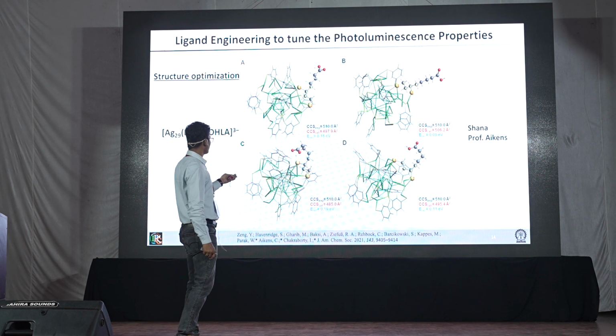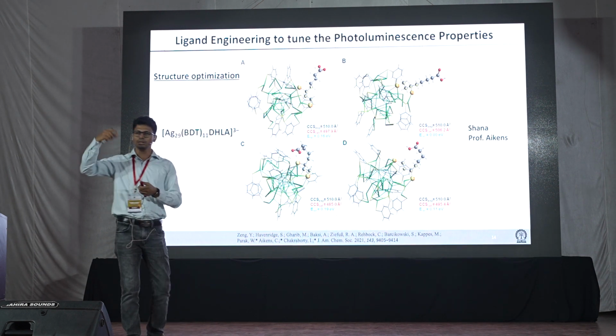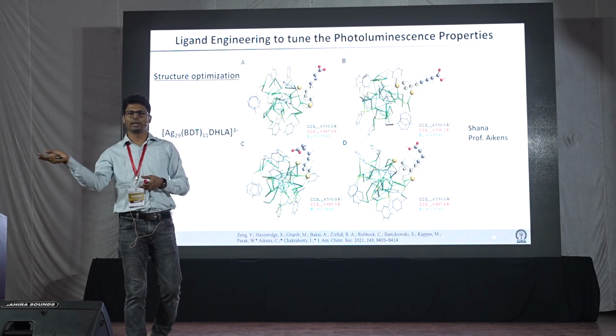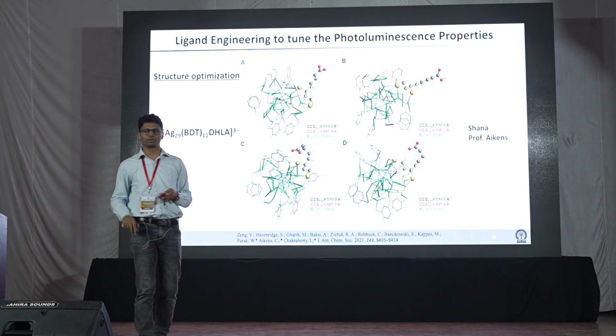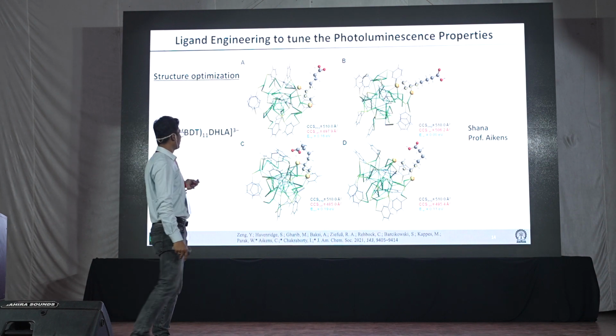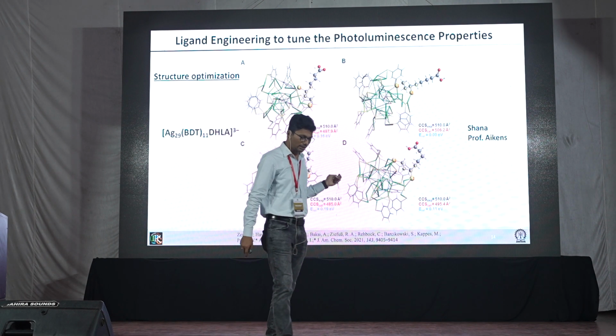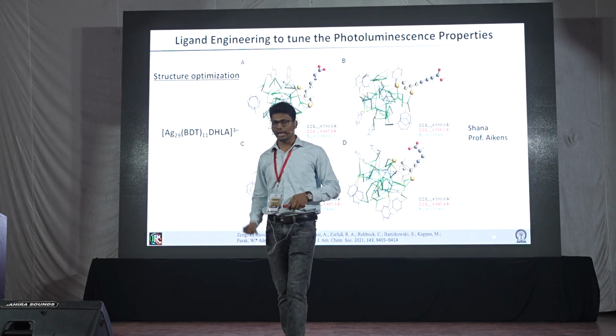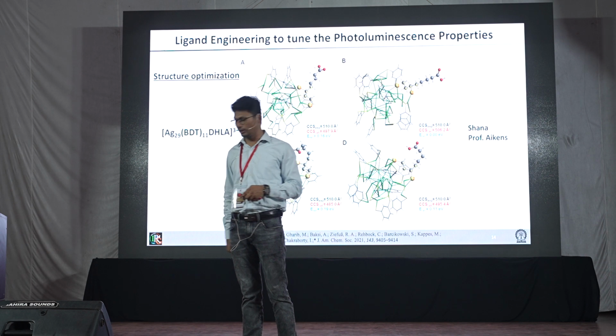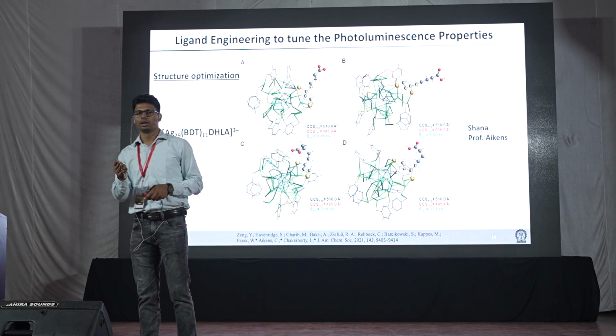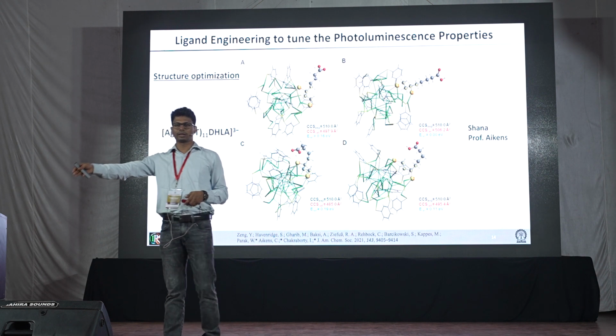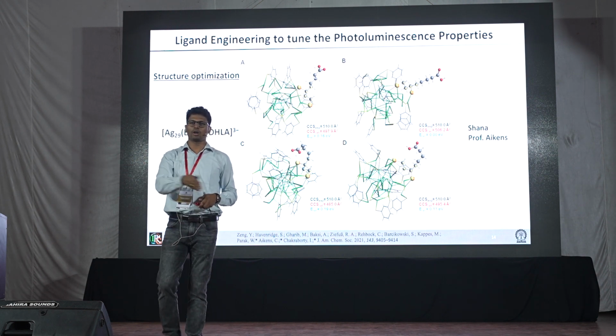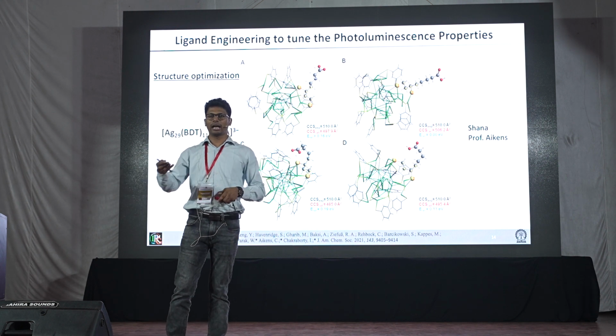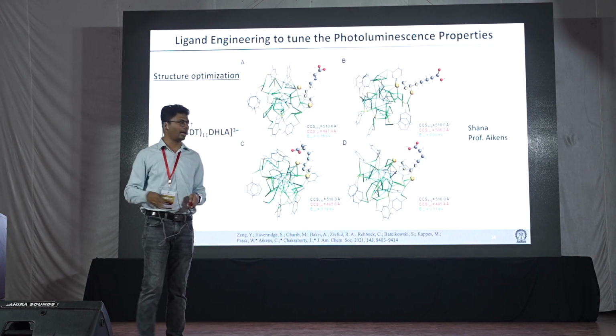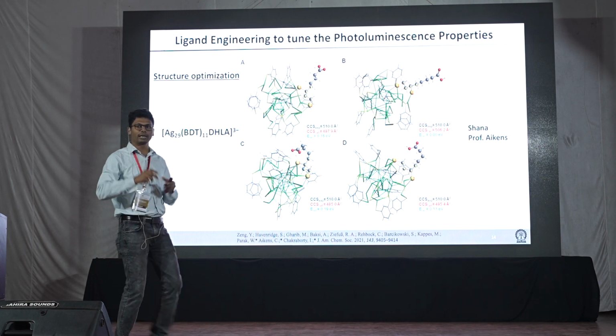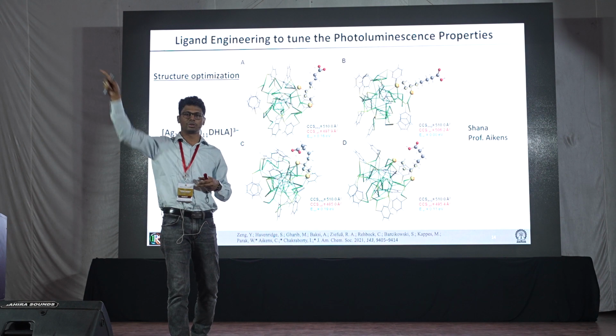And with this, we tried to come up with a solution, because the carboxyl group, if you exchange the lipoic acid, might be placed in many orientations. And from there, what we found is that this is probably the best possible way, where you have the 0-0 relative energy. But again, it's one of the important points I should mention here, that these are dynamic processes, right? We cannot assume solution-based chemistry directly applies to gas-phase chemistry, because gas-phase chemistry might differ. But we do agree, and there are a lot of other reports which suggest that solution-phase chemistry can be reflected in the gas phase. So sometimes we have to rely on that, and keeping that in mind, this is probably the best possible direction of carboxyl group anchoring, opposite to the metal surface.